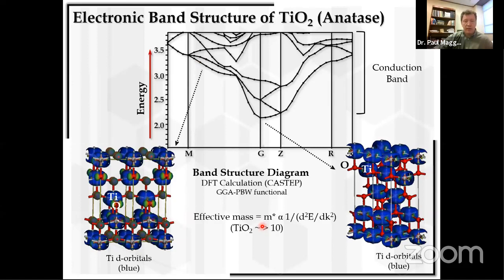So the upper part of the band here, I've plotted out the electron density, and you can see that there's a significant overlap now of the titanium electron density in blue, and then the oxygen electron density in this green shaded region. You can see it's shaped like a p orbital, just as what you would expect.